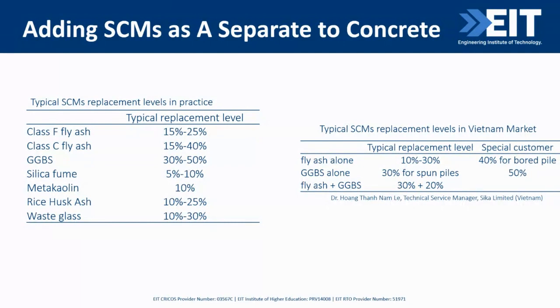Fly ash is used in more than 50% of ready-mixed concrete nowadays. Class F fly ash is often used at a dosage of about 15 to 25% by mass of cementitious materials, and class C fly ash is used at a dosage of 15 to 40%. Some concrete may contain higher volumes of fly ash, more than 40%. The dosage varies with the reactivity of the ash and the desired effects on the concrete.